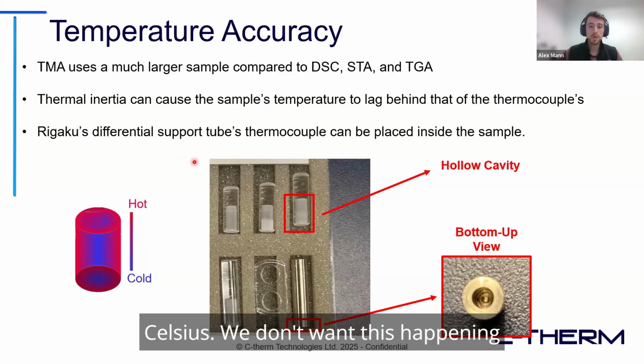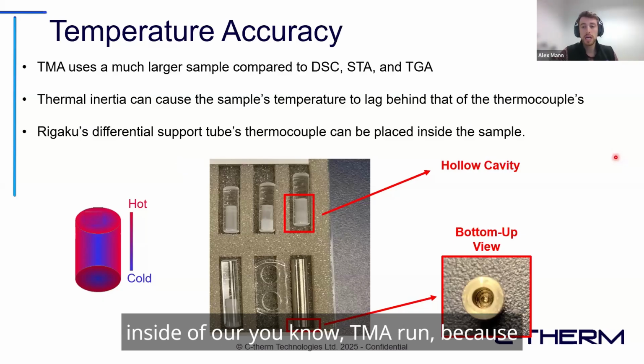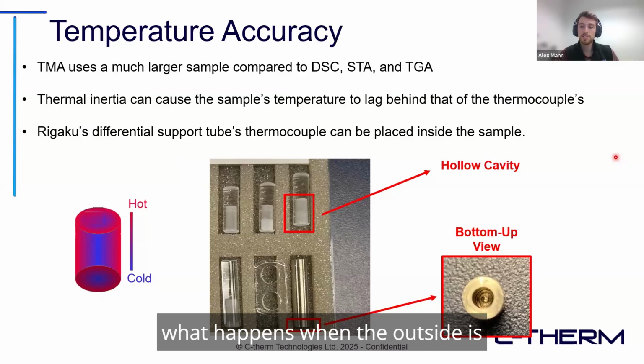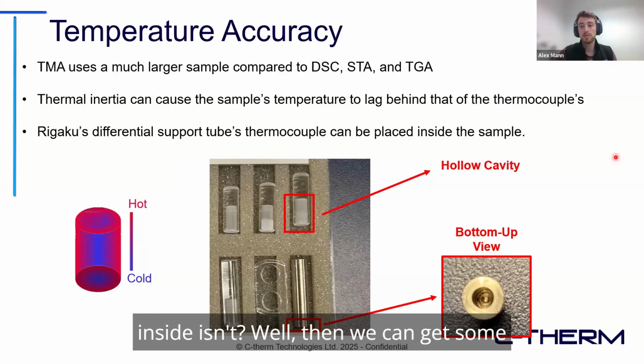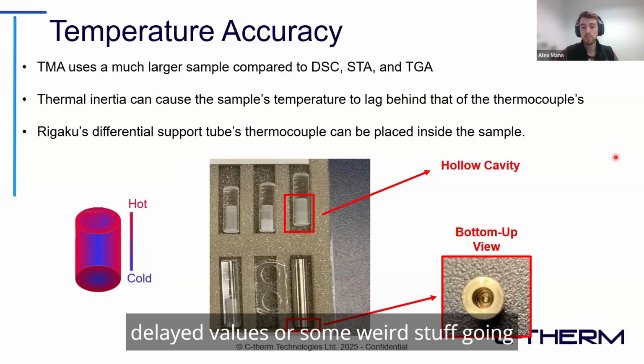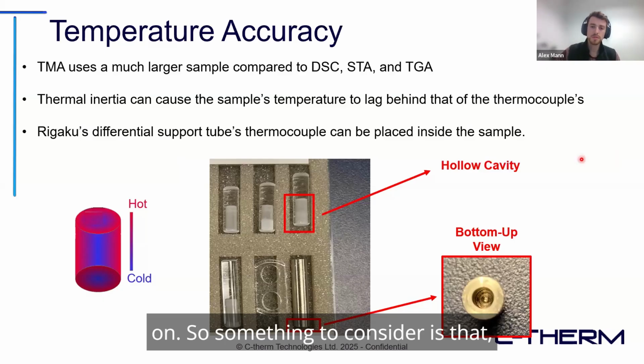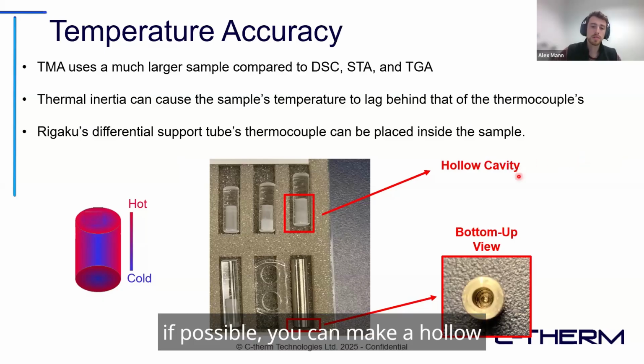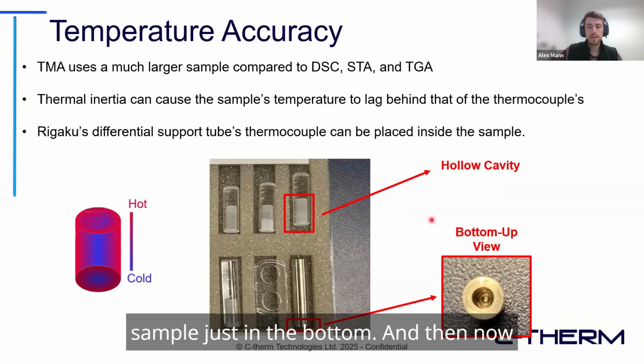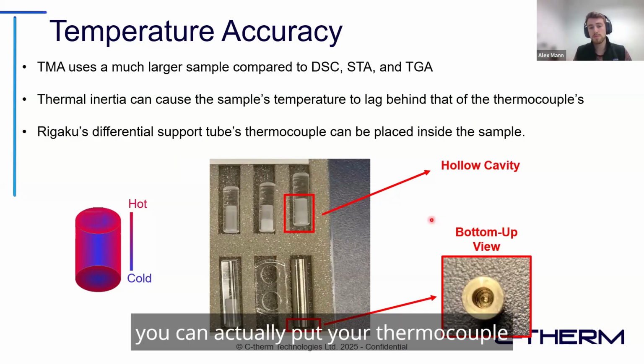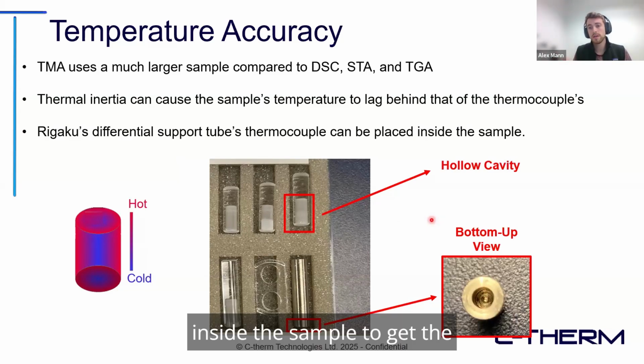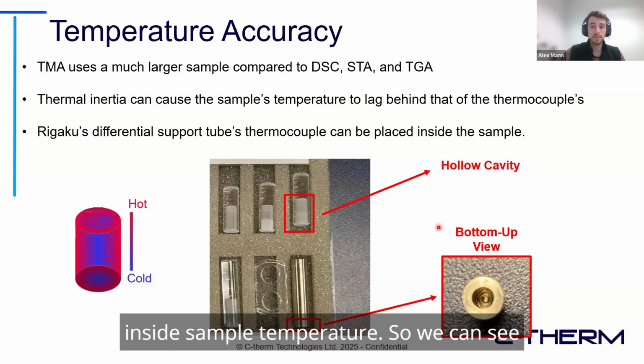We don't want this happening inside of our TMA run, because what happens when the outside is undergoing glass transition and the inside isn't? Well, then we can get some delayed values or some weird stuff going on. So something to consider is that if possible, you can make a hollow sample just in the bottom, and then now you can actually put your thermocouple inside the sample to get the inside sample temperature.